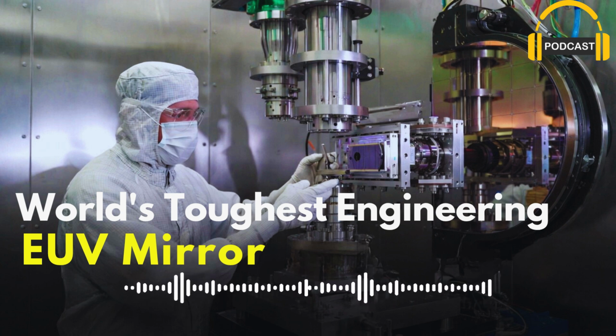But even with all that, the mirrors still had tiny imperfections, mid-frequency roughness that scattered light and reduced contrast. It took years of tiny improvements, from 0.2 nanometers roughness in 2005 prototypes down to 0.15 nanometers in 2007, and finally around 0.05 nanometers by 2011. No big eureka moment, just relentless, boring, expensive tweaking.